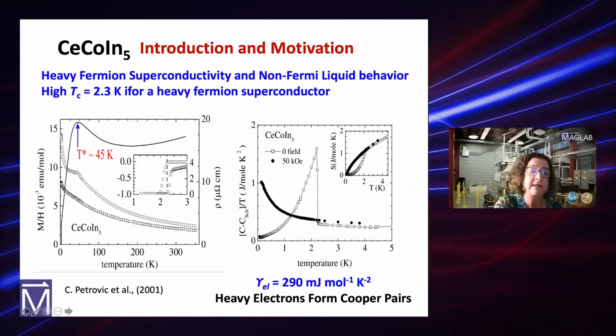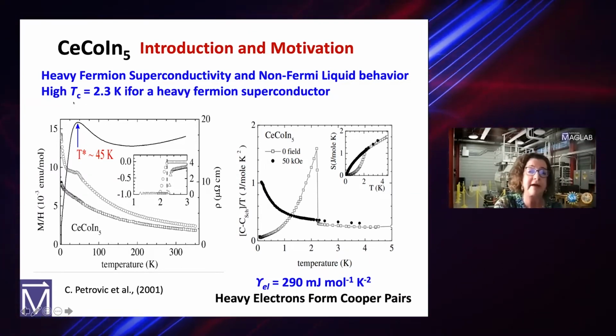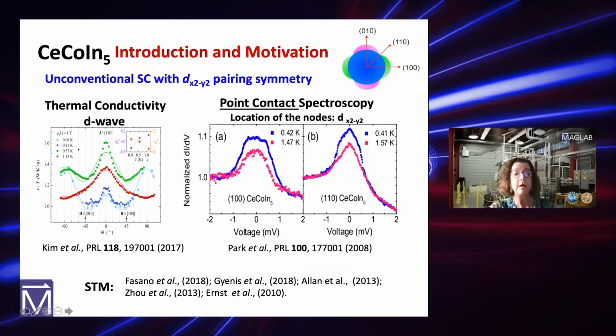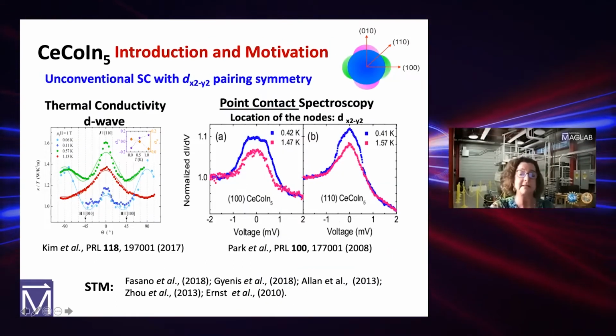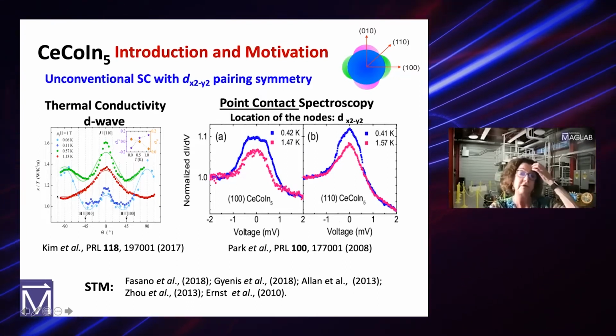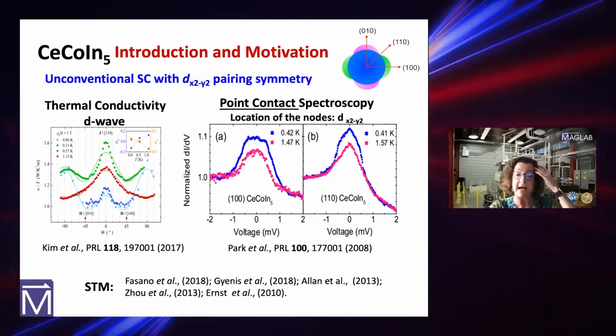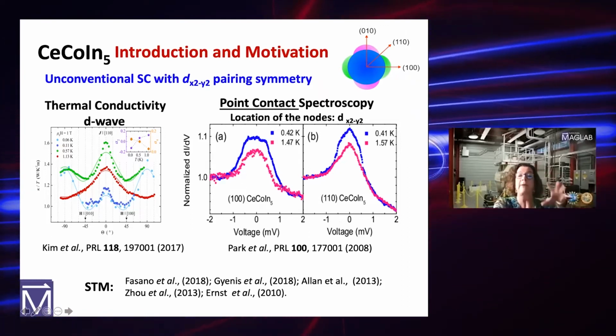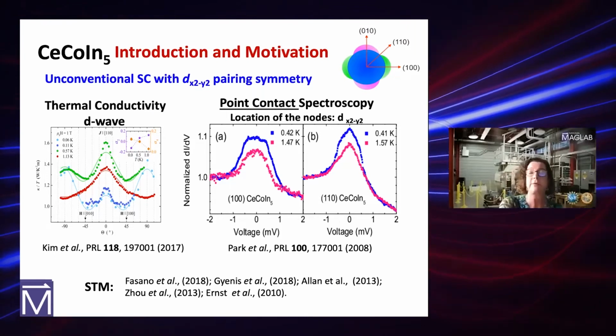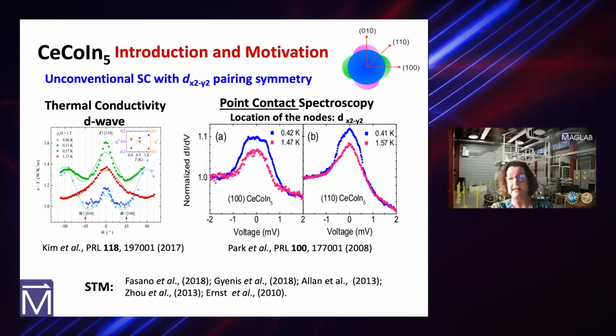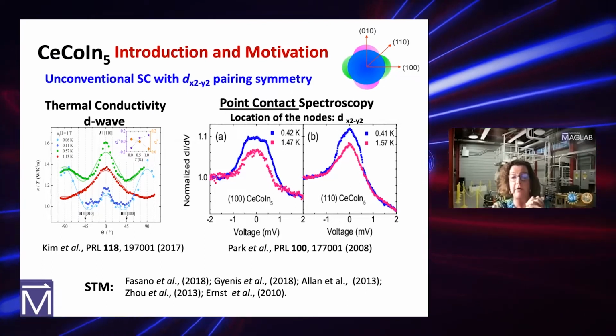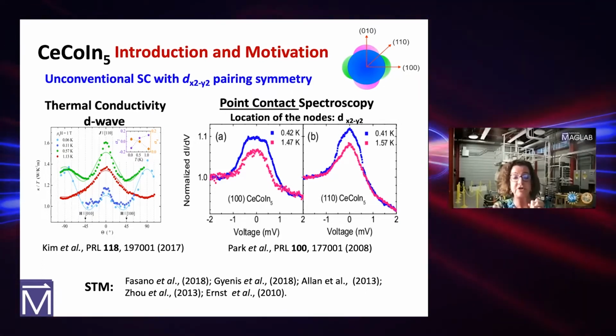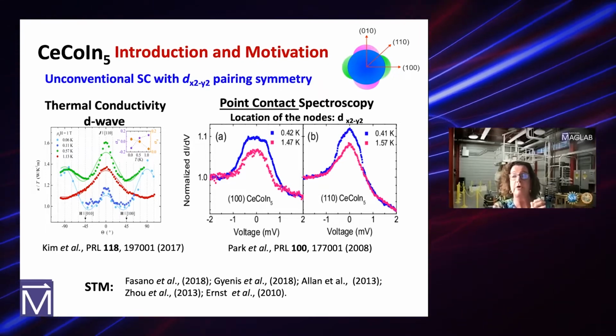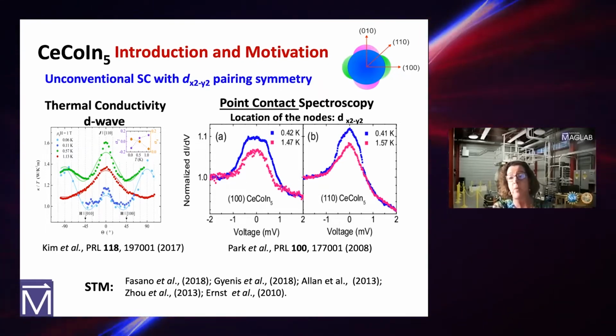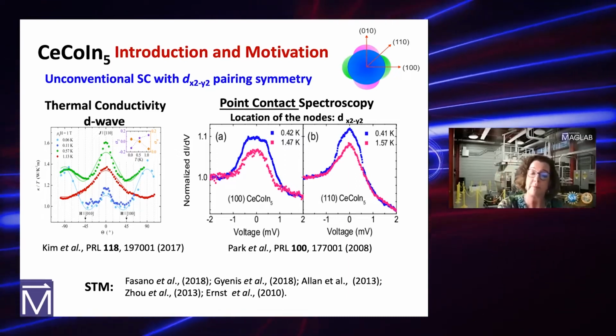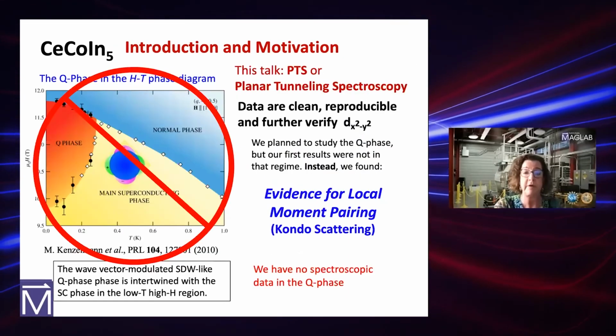Just to remind you, the T star is about 45 Kelvin in this material. We looked at this a long time ago, and people have studied this and discovered that they were d-wave due to thermodynamic measurements. We did some point contact spectroscopy a bunch of years ago, and by the shape of the quasi-particle scattering in this measurement we were able to locate the nodes, dx squared minus y squared. There are STM measurements listed on the bottom that also show that this is a dx squared minus y squared symmetry order parameter in the superconducting state. So we're in agreement on that.